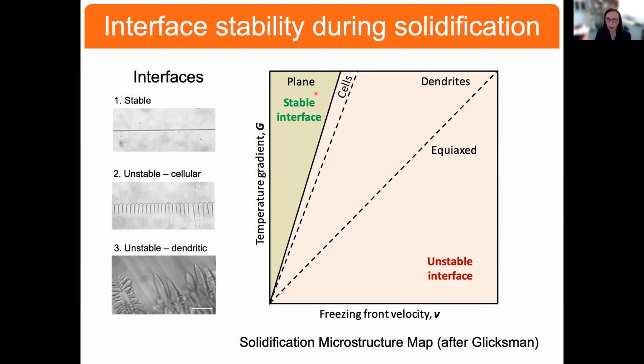And what we see here are various regimes that describe the interface. If you can freeze things very, very slowly over a given temperature gradient, the freezing front is basically horizontal, but it requires very low freezing front velocities. If you increase this velocity, basically there are perturbations along the freezing front, and you begin to see this unstable freezing front that at first appears cellular, which is what you see here on the left. And if you go further, you end up seeing what I consider to be very beautiful dendritic structures.